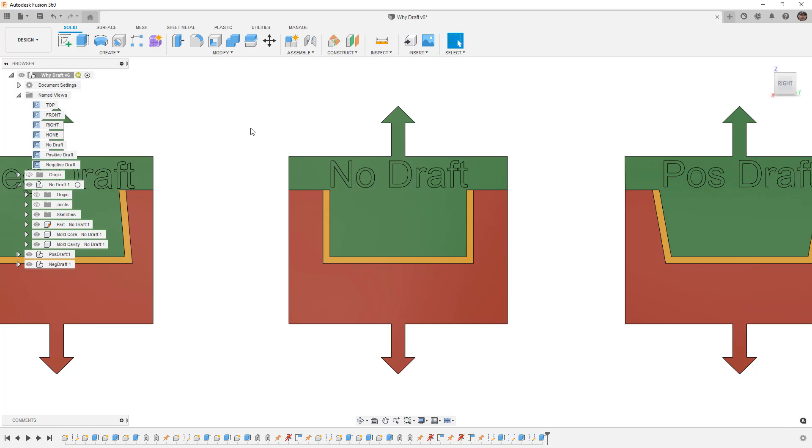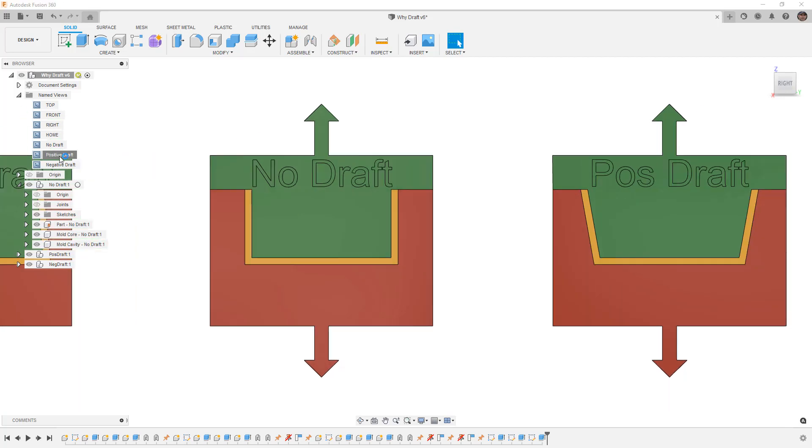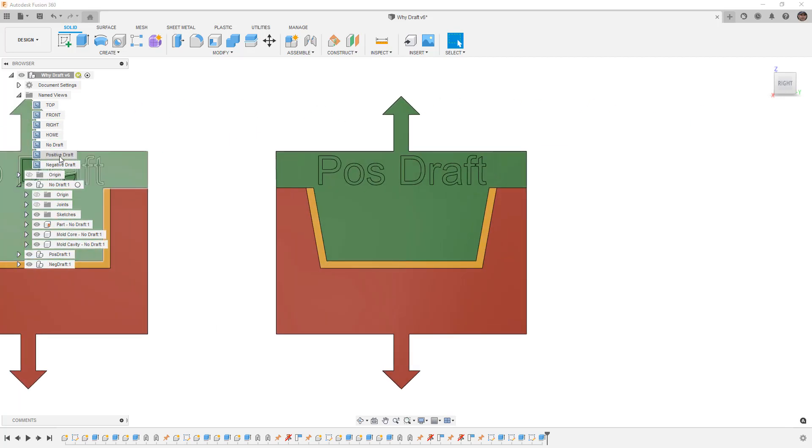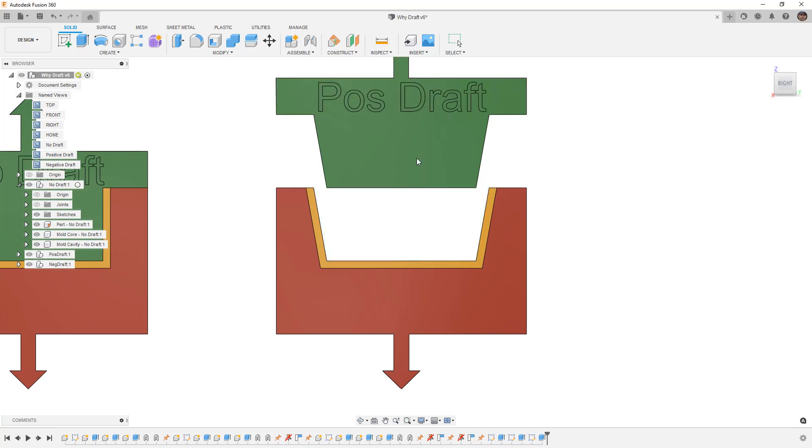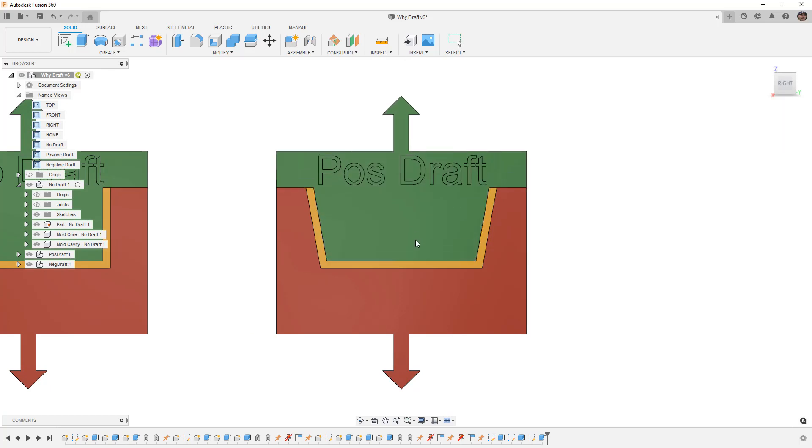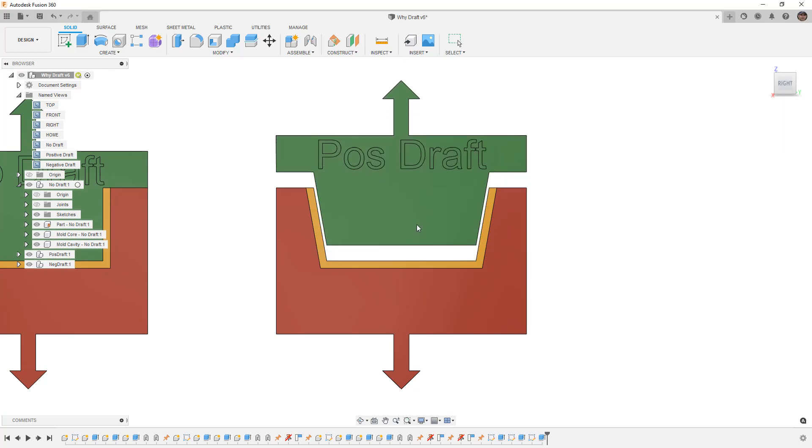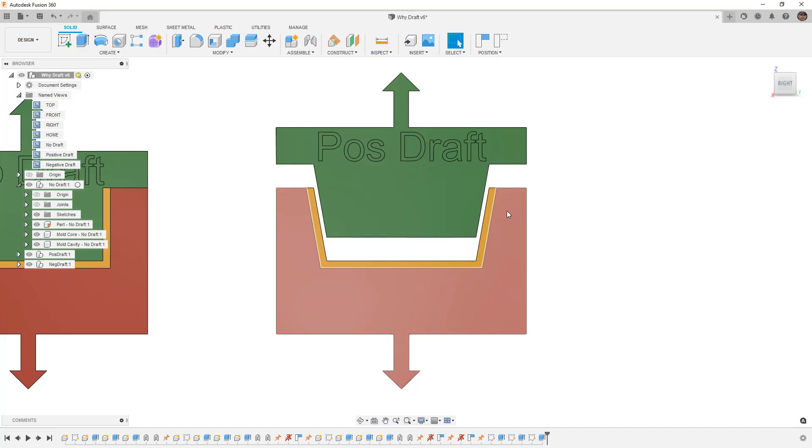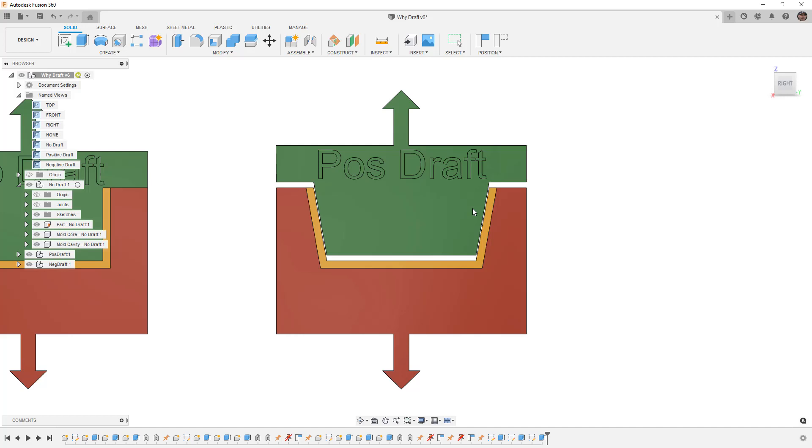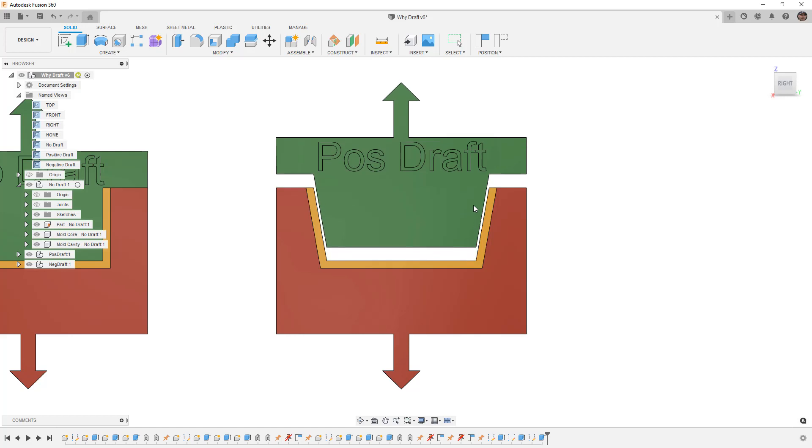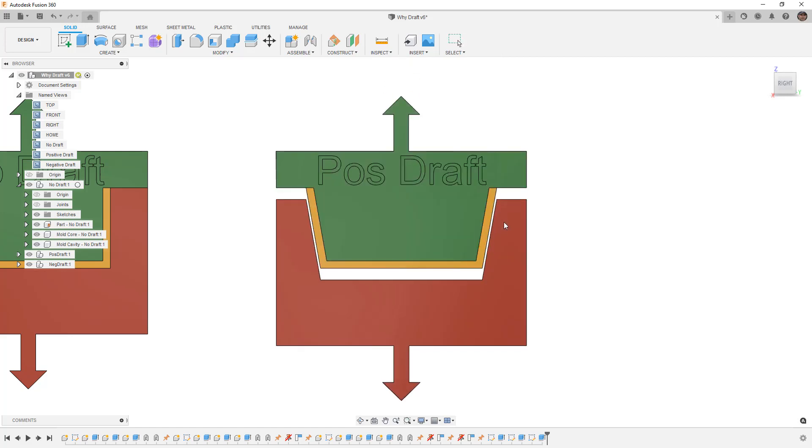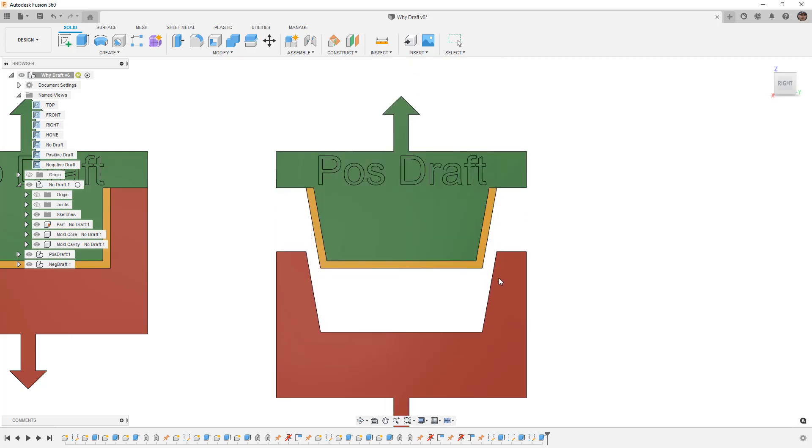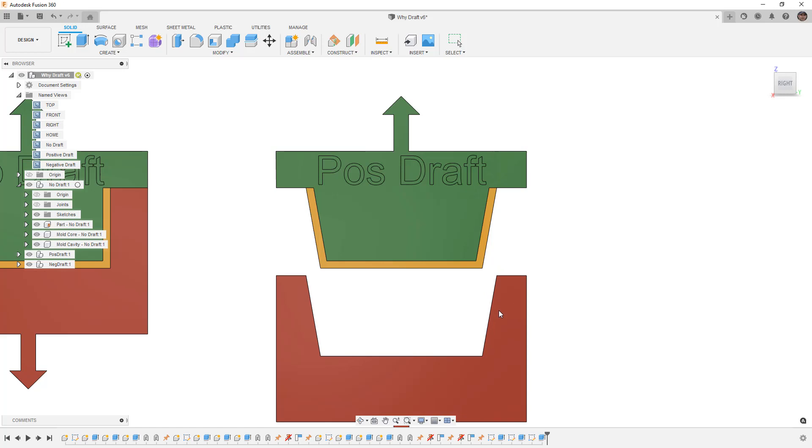Unless there's a very critical feature that is usually non-cosmetic on the inside of a part that needs to have no draft, we do want to avoid this. When we look at the positive draft, again we have a core and a cavity. As we pull the core out, you can see it gets further and further away from the part because of the draft. In this case we have 10 degrees on this wall. In general we'll probably have somewhere between 1 and 5 degrees at most, but this gives us a good representation.